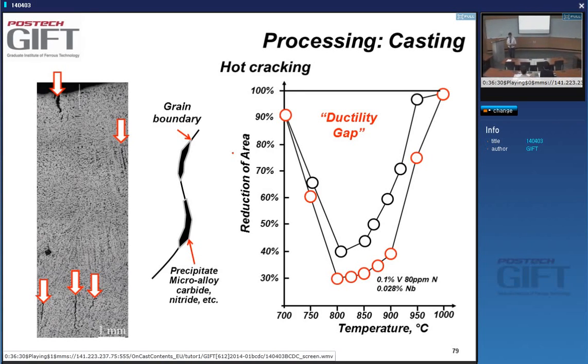You can get other cracks developing in the material. You remember that when you cast a slab, in many of these equipments, you bend it. So you actually put deformation on the material. What happens? Well, you can get cracks. This is an example here where it's really bad, a good example of a bad slab, with big cracks in a slab.